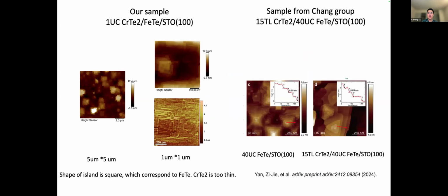And here's our AFM result of 1 unit cell chromium ditelluride on iron telluride. The island shapes are square, which matches the iron telluride structure, which means the chromium ditelluride is too thin to show up clearly. For comparison, we compare our sample with Professor Cuizu Chang's AFM results. They grew 15 layers of chromium ditelluride on 40 unit cell iron telluride. So in their sample, the iron telluride shows a perfect square shape, and the chromium ditelluride shows a perfect triangle shape, which is different from ours. Which means in our sample, the chromium ditelluride might be too thin to show up clearly.